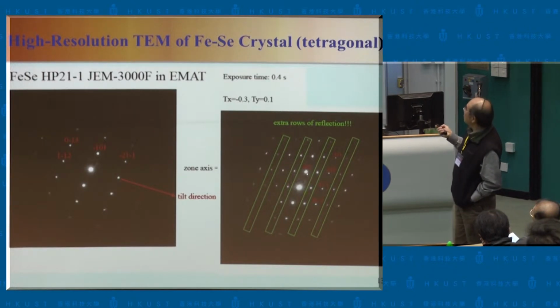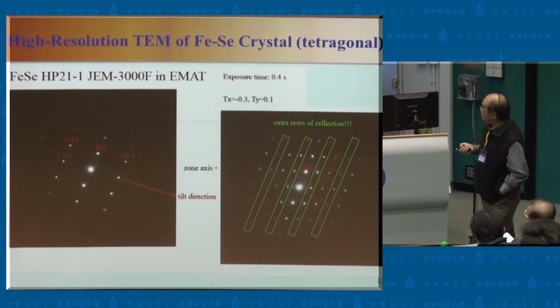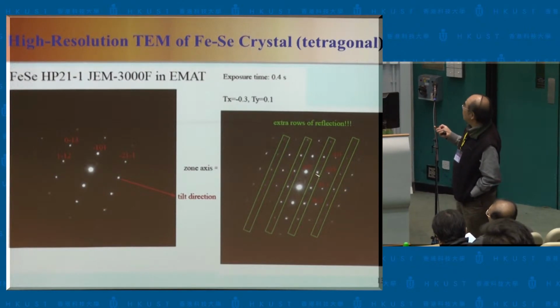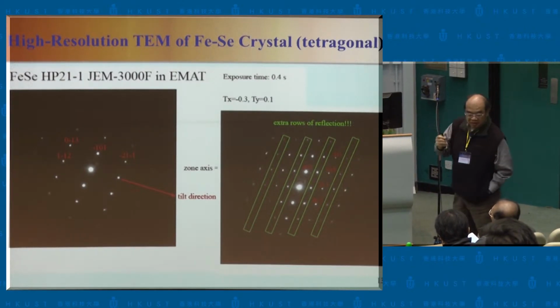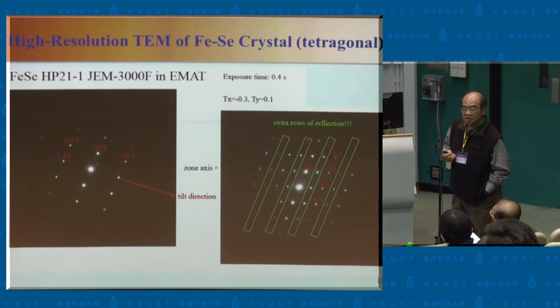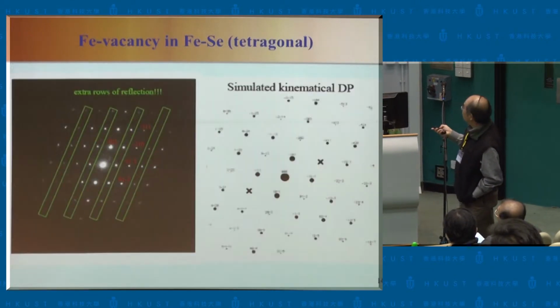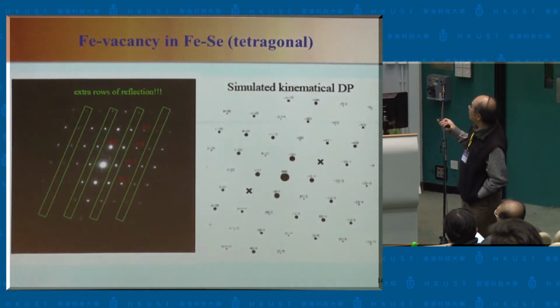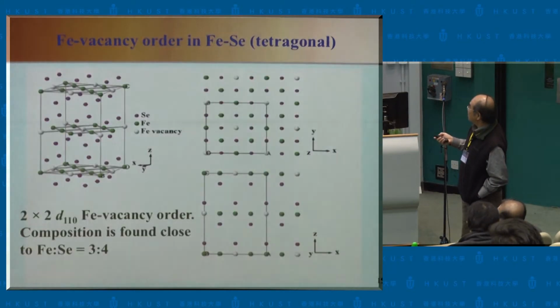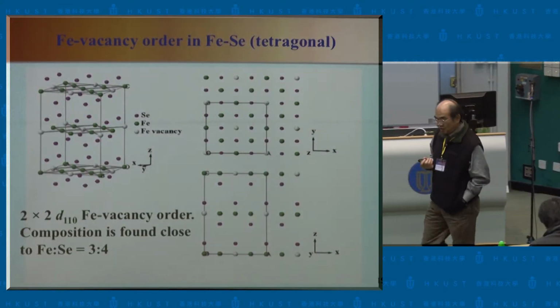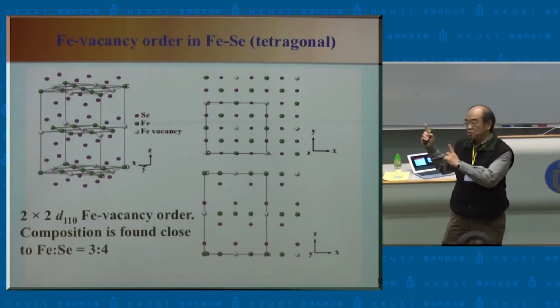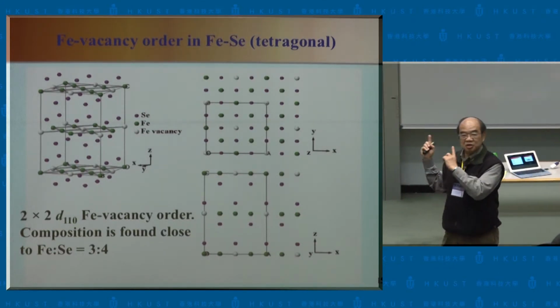And we found indeed there is a very interesting extra peak in this TEM image, showing that there's some kind of superstructure that is indicating some kind of iron vacancy. And one of my associates made a clear simulation of the system and decided that there is a 2x2 iron vacancy order. And this one actually is not superconducting for this particular one.